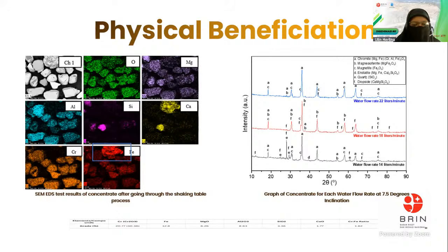Then the XRD of the physical beneficiation. The chromium to iron ratio is improved from 0.9 to 1.62, and the chromium content from 8.5% improved to 20.77%. This optimal result is then followed by the thermal beneficiation.